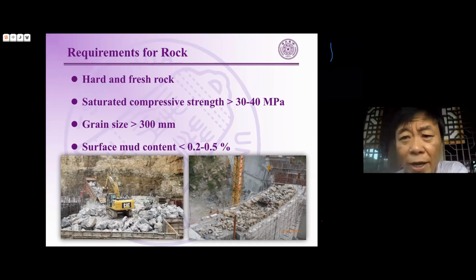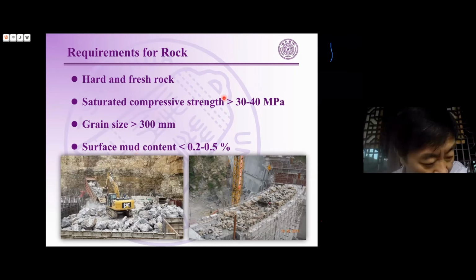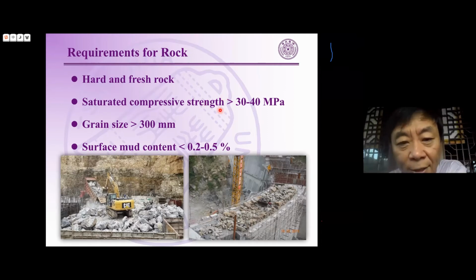What is hard? For a concrete dam lower than 100 meters high, the saturated compressive strength of the rocks needs to be larger than 30 to 40 megapascal. The 30 and 40 megapascal is very easy to meet for usual rocks, and the grain size will be over 300 millimeters, and the surface mud content must be lower than 0.2 to 0.5 percent. So these are the requirements or criteria for the large rocks.